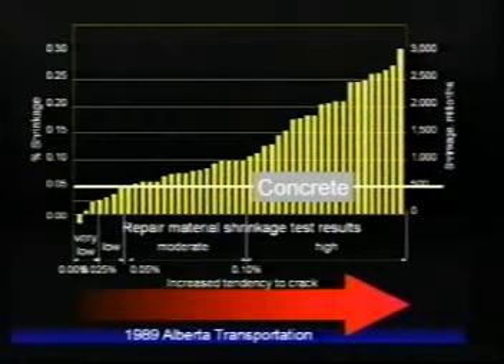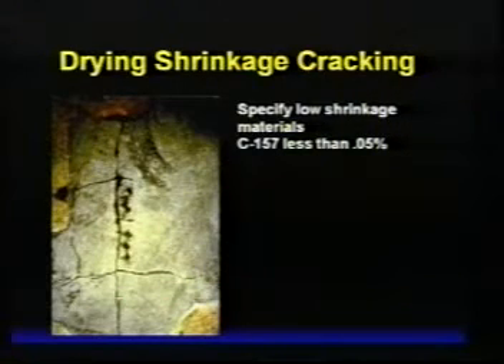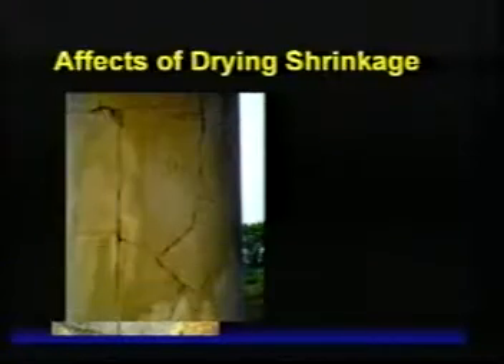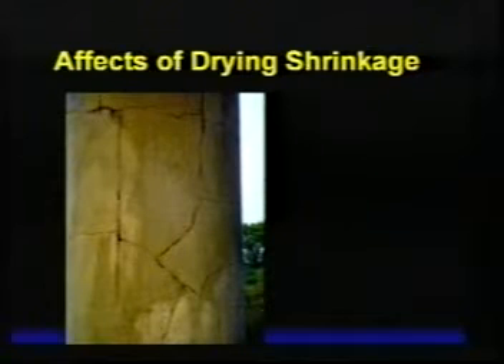That's really due to the fact that you have a well-graded, larger aggregate than a lot of the prepackaged materials represented in these 46 materials, which are generally more fine aggregate, more cement content. These are the effects of the shrinkage. You can see the shrinkage cracks. This is a horizontal repair, and these are some vertical repairs. They basically manifest in these cracks that really bring into question the viability of the repair work. So we want to avoid these by selecting materials with low shrinkage.